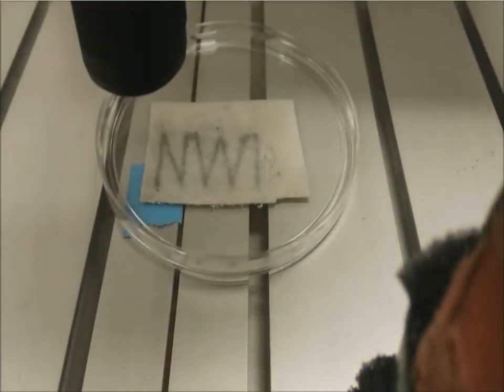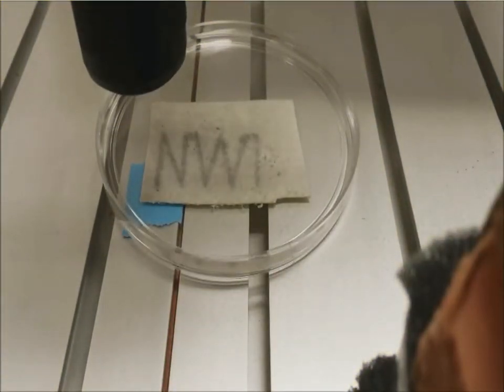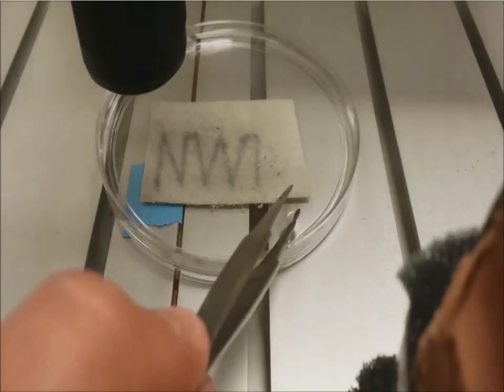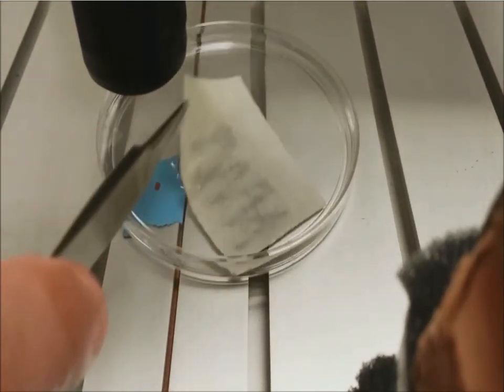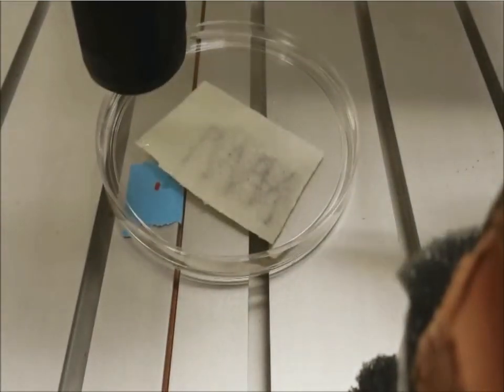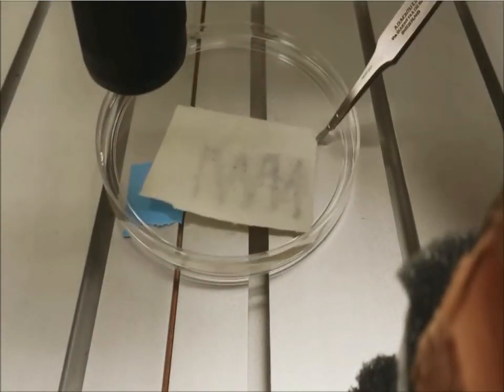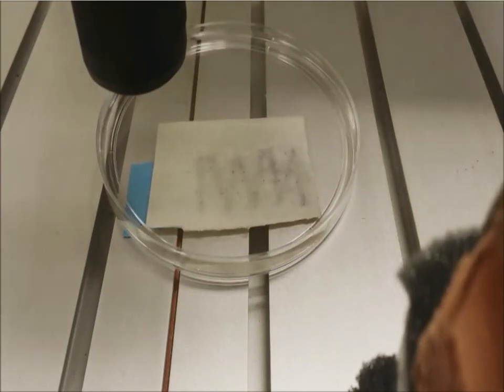And you can see that we're now reducing the silver within this pattern. You can see it right here. So now we're writing electronic patterns onto the semiconducting coatings. We're starting to build out these more complex structures, as you see here. We've actually got a little bit more perfected than this video shows. You can get it all the way through just by changing some of the textile structure as well as how much energy, or how much wattage of a laser pointer, they're using.